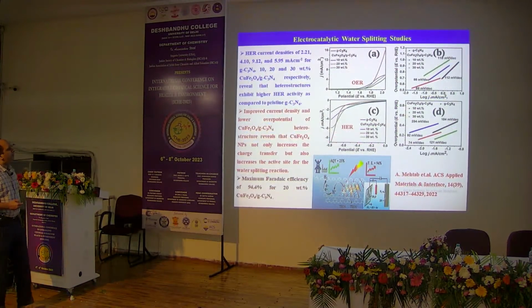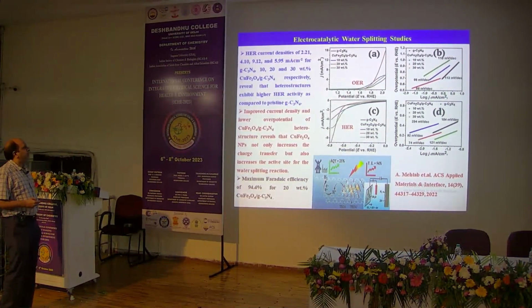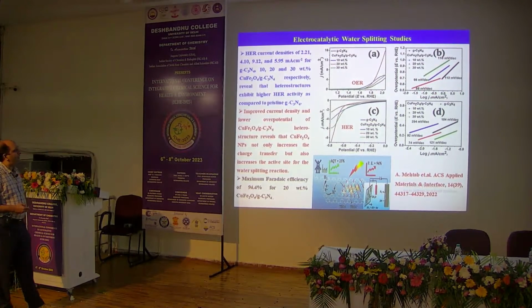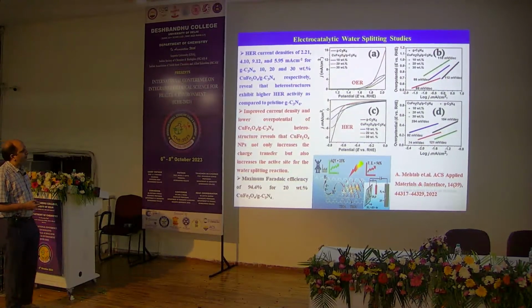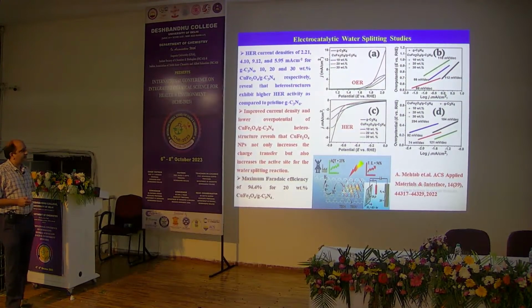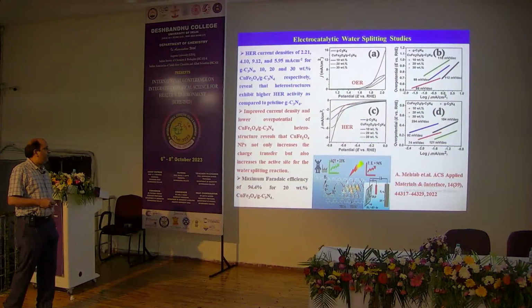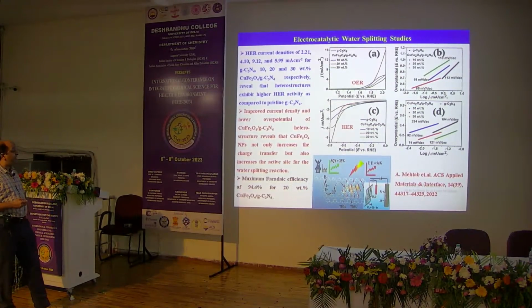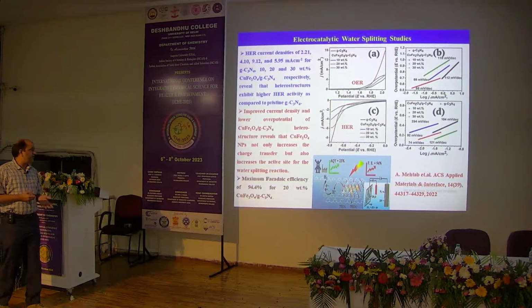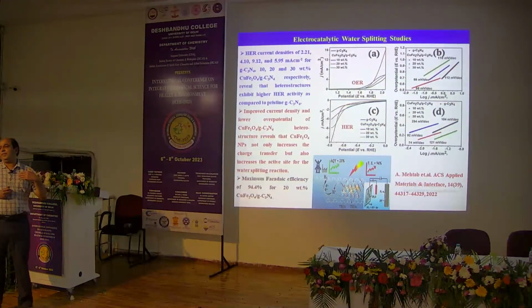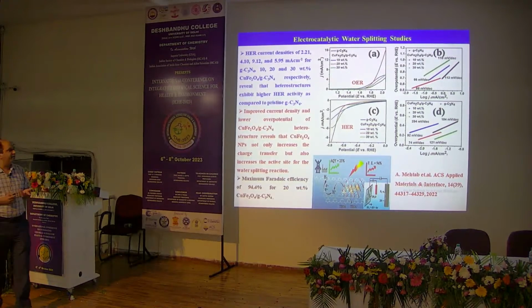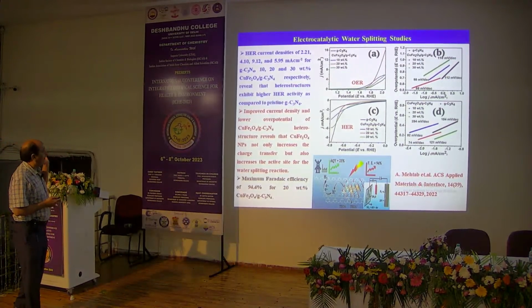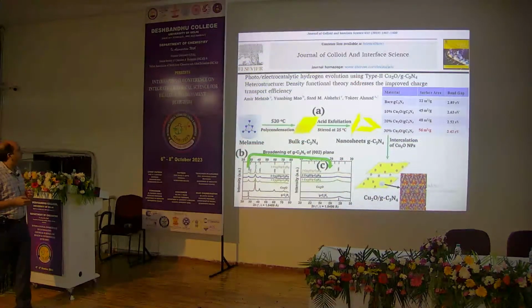So this is the OER plot for the copper ferrite graphitic carbon nitride heterostructure, and the corresponding Tafel slope, and this is the HER and the corresponding Tafel slope. So these studies give a low onset potential and improved current density, which signifies high HER activity. And we also obtained the maximum Faradaic efficiency for the 20% copper ferrite over graphitic carbon nitride, which refers to the free electrons in the conduction band for making the significant photochemical reaction that we discussed in the earlier slide.